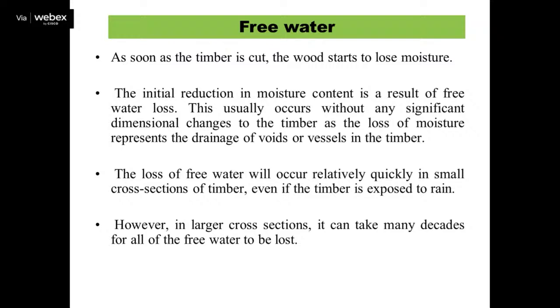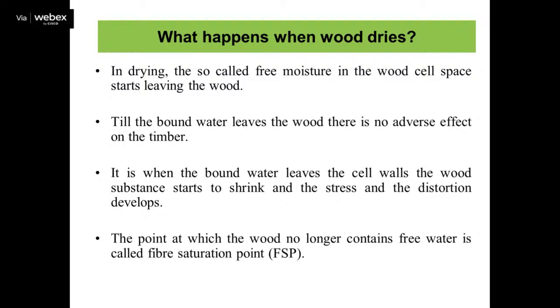However, in a large cross section, it can take many decades for all the free water to be lost. As I told, the free water which goes from the voids or the vessels or the cells does not cause shrinkage and swelling in the wood. But once all the free water is gone, the water which remains present in the cell wall is called the fiber saturation point.